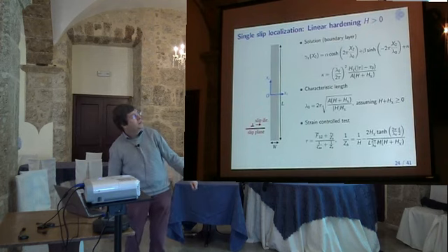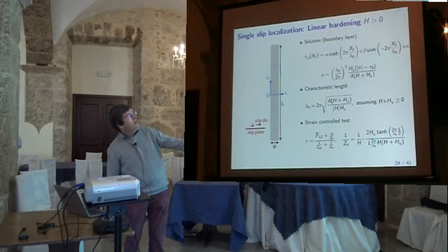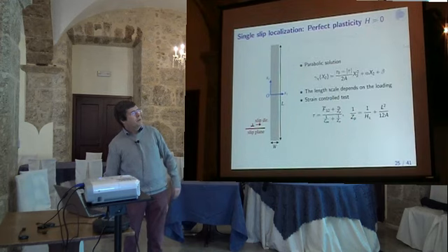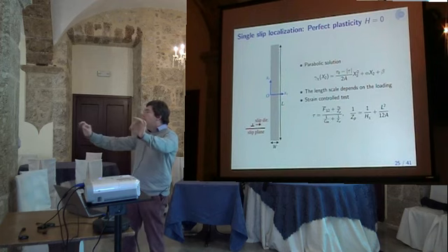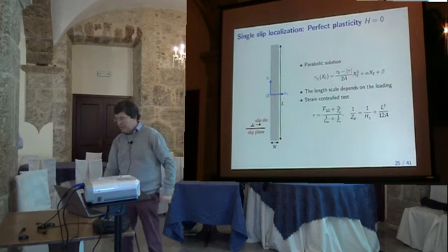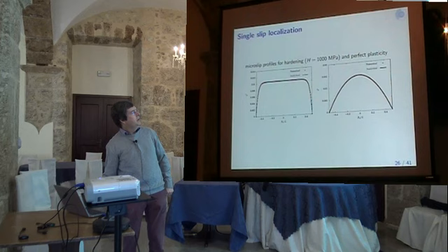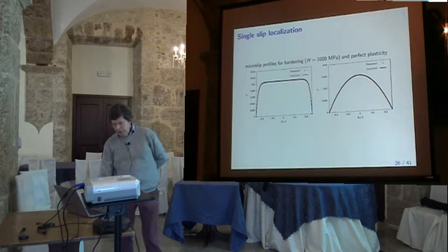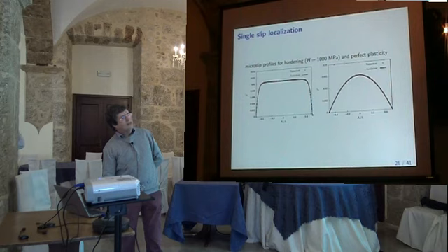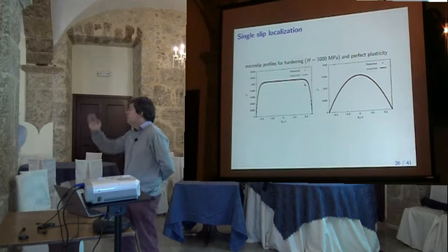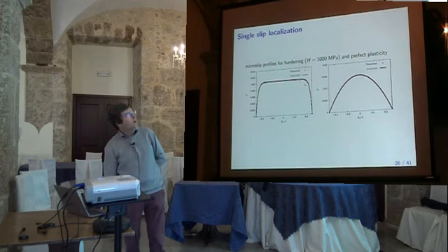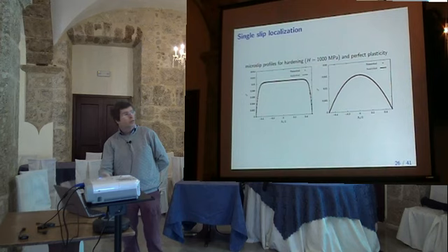Here it is intrinsic, because the length scale depends only on the moduli, in fact. But in this case, it will depend on where you pin the plasticity. Okay, so these are the results. Hardening modulus, I have put some Dirichlet boundary condition, 0 slip here. So you have a boundary layer. There is no localization, of course, because it's hardening. So you have simply a boundary layer here. So this is the solution.